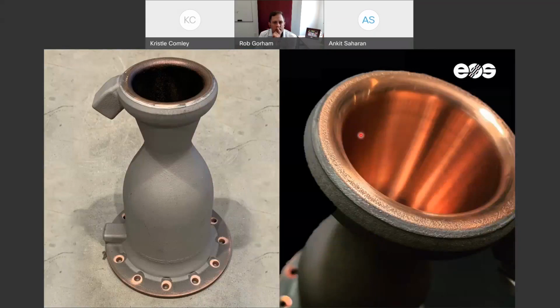Now, when I was talking about the rocket side, the holy grail right now is bimetallic alloys. Additive is not traditionally known for bimetallic alloys, but what Launcher did was build this copper, chromium, zirconium part. It can withstand high temperatures and conduct heat. It can probably withstand high pressures, but not at the pressures that they want. To alleviate that problem, they sprayed it with Inconel powder, a thermal spray process. The Inconel powder coating helps with withstanding pressures while keeping the high conductivity you would expect from copper alloys.